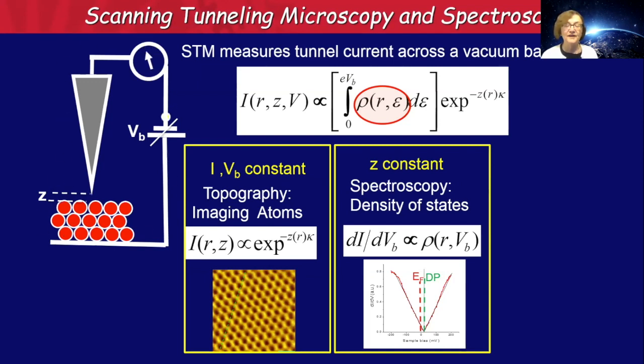The Dirac point here is the minimum of the density of states, and the Fermi energy in these kinds of measurements is always designated as the zero of energy. So here we have a nice separation between the two energy scales, and depending on what gate voltage we apply, we can move the Fermi energy with respect to the Dirac point.